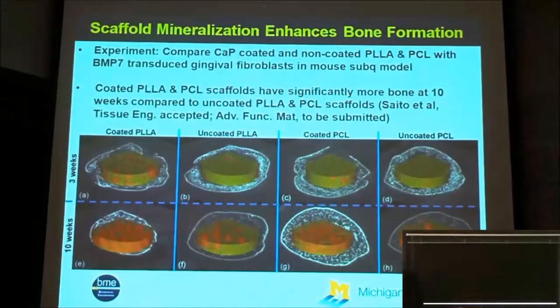The other thing we looked at is functionalization. So can we functionalize these scaffolds, put on calcium phosphate coatings or put on different growth factors? Again, this is work with Bill Murphy where we took, and the advantage of having the controlled design is we can make PLLA scaffolds and PCL scaffolds with the exact same architecture. So that's not a confounding variable. And then we've made some scaffolds with the calcium phosphate coating, some without, for both the PLLA and the PCL. Again, we put this in the immunocompromised mouse model. It's a very powerful osteogenic approach, putting in this gene therapy. And what you see is that the coating has a huge difference in terms of the bone growth. The coated scaffolds show statistically greater bone growth, as you see here, than the uncoated scaffolds.